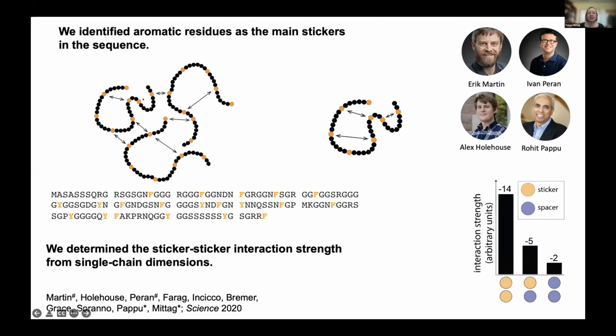And we decided that we'd be able to find the interacting motifs in individual proteins. We didn't actually have to go to the dense phase, because the same interactions that would drive phase separation intermolecularly should also be satisfied intramolecularly and compact the protein molecules. And our data, which I'm not going to show you because it's been published a while, really pointed to the importance of aromatic residues in the sequence that I've highlighted over here. And we made a bunch of mutations in which we changed the number of these aromatic residues and measured the single chain dimensions of these proteins and really saw that the single chain dimensions changed. And this allowed Alex and Rohit to extract interaction strength, sticker interactions, but also sticker-spacer and spacer interactions.